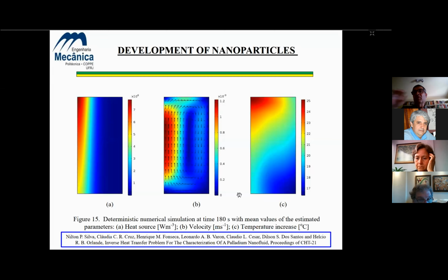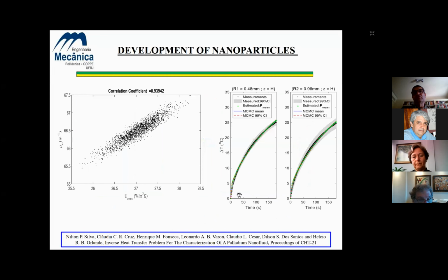So although most people use mean temperatures for the estimation of those quantities related to those nanofluids, we use the inverse analysis based on this natural convection model to estimate different parameters of the model. And by using only non-intrusive measurements taken with the infrared camera, which actually agree very well with the model after the parameters are estimated, as shown by these two figures.